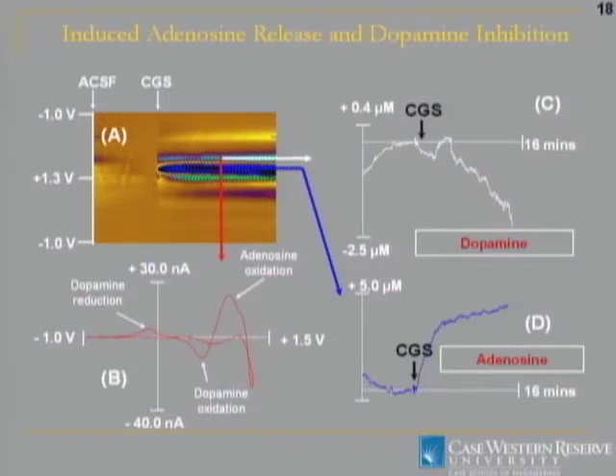Sorry, do that one first. So it went up, like I showed you in the last slide. The dopamine concentration, there's a lower potential for oxidation. It went down. That's why it's shown as a negative peak, even though it's an oxidation, because it's relative to the background level, and that's shown here. So it's interesting that we can see these both simultaneously.